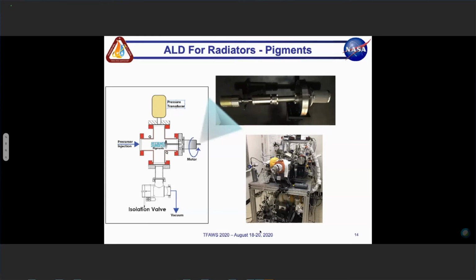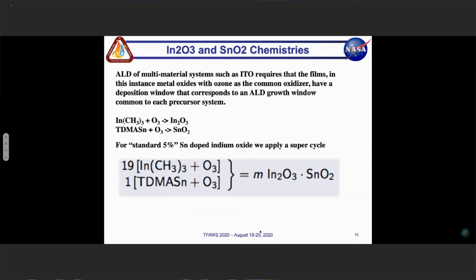dissipation path. So the way we're able to do that is, this is our typical little reactor that we have, where we have these pigments inside of a rotating mesh basket. So the pigments are being rotated, and we inject within this chamber our two materials which allow us to grow our charge mitigating coating. In this particular case, it's going to be indium oxide. It's an interesting thing about the way that we operate. The rotating basket itself is nothing fancy. We actually went to IKEA and used a tea basket to hold our pigments, and it worked out just fine. So back of the envelope, what I call dirty engineering.